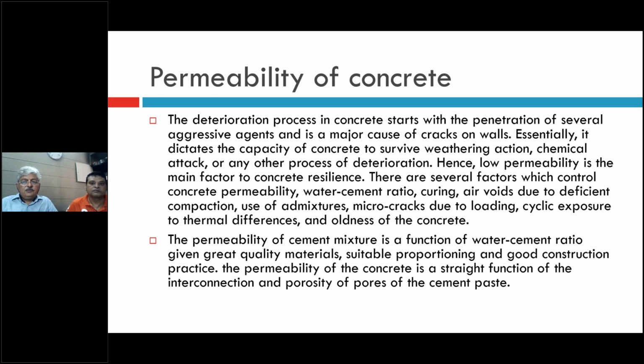There are several factors which control concrete permeability. Number one, water cement ratio. Number two, curing. Number three, air voids due to deficient compaction. Number four, use of admixtures. Number five is micro cracks due to loading. Number six is cyclic exposure to thermal differences and oldness of the concrete.